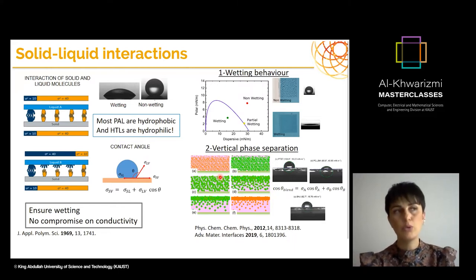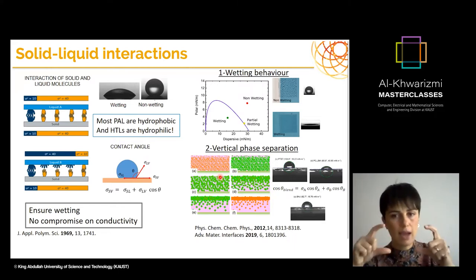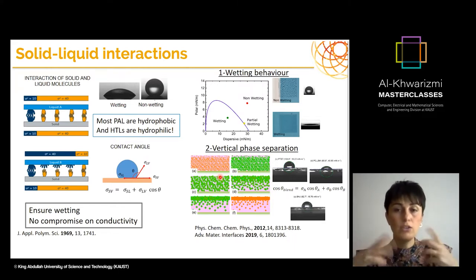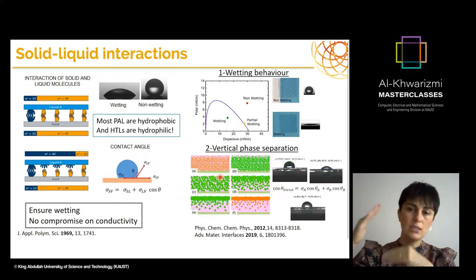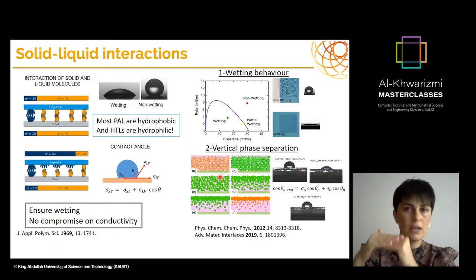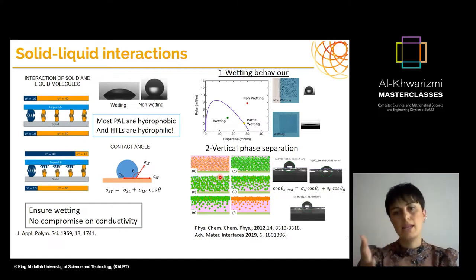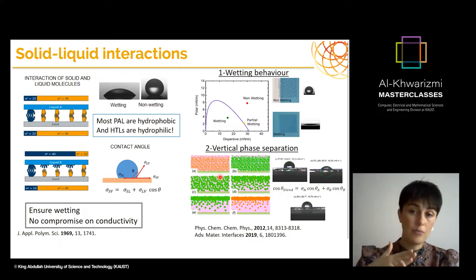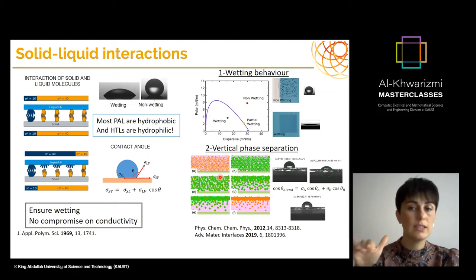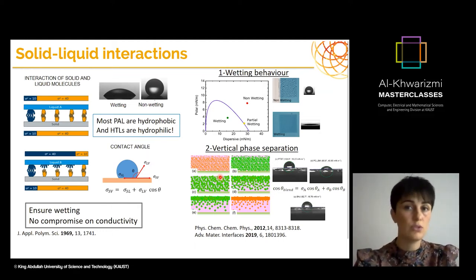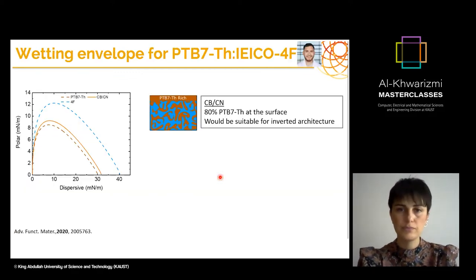And why is this so important? Because in the photoactive layer, we need to have an effective charge separation, and the P-type material should go to the P-type side, which is the hole transport layer. And the N-type material should go more towards the electron transport layer. And if that is not the case, then you would have this vertical phase separation, which hinders your charge transport.